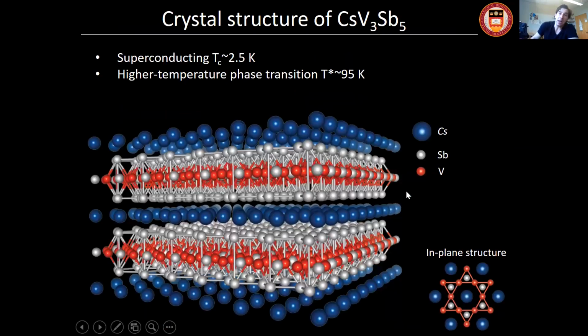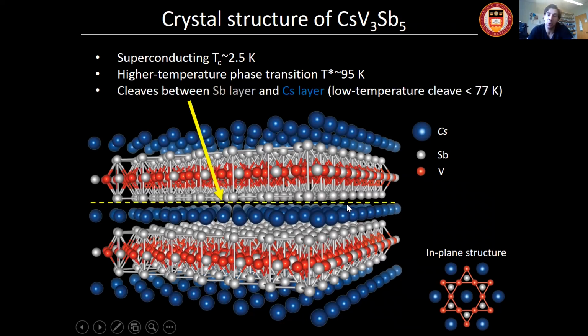Okay, so the first material and the first part of my talk involved this CsV3Sb5. It's superconducting, with a superconducting transition at about 2.5 Kelvin. And it has a higher temperature phase transition of about 95 Kelvin, which, based on XRD even at the time, was related directly to probably some kind of charge density wave. So we take single crystals from Stephen Wilson's group, we put them in vacuum and then we cleave them to rupture them right here. The vanadium antimony sheets are actually pretty tightly bound, so what we find is that the crystals typically cleave here. We have to cleave them at very low temperature. So the lower, the better.